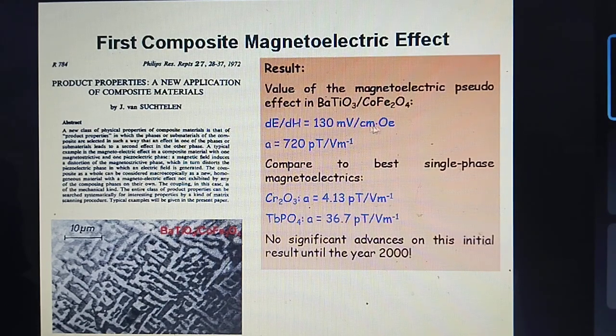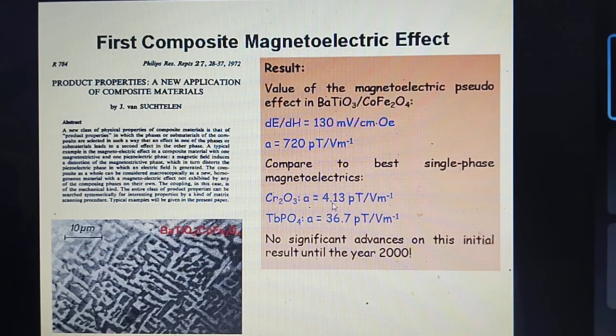So if you see the magnetoelectric coupling, this is the coupling between the magnetic and electrical effect, which is measured by dE/dH of T. It has a value of 130, whereas its coefficient has a value of 720 picotesla per volt per meter. And if you compare the value of alpha with a single phase multiferroic material, you can see its value is 4.13. TbPO4 has a value of 36.7, whereas there is a tremendous change in the value of this alpha, which goes up to 720. So multiferroic composites, that is a composite consisting of the ferroelectric properties and the magnetic properties, can be combined together.